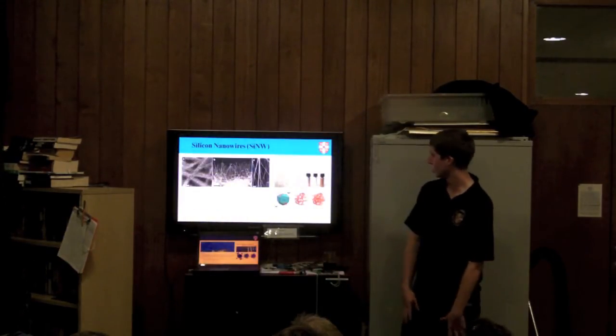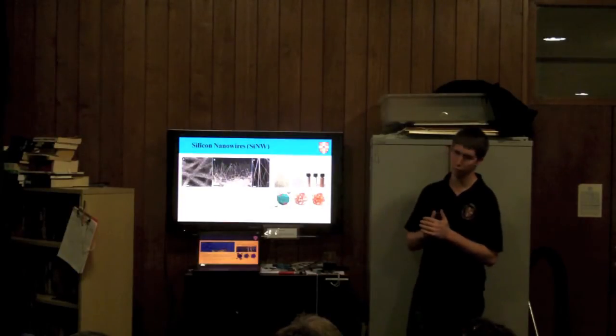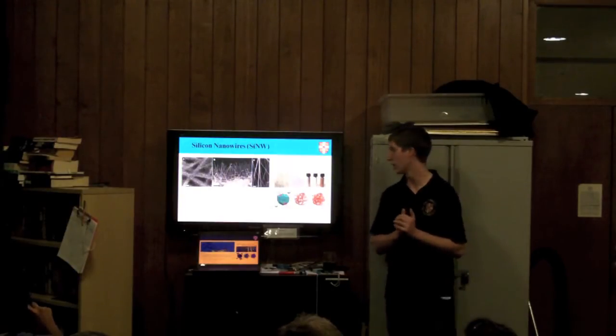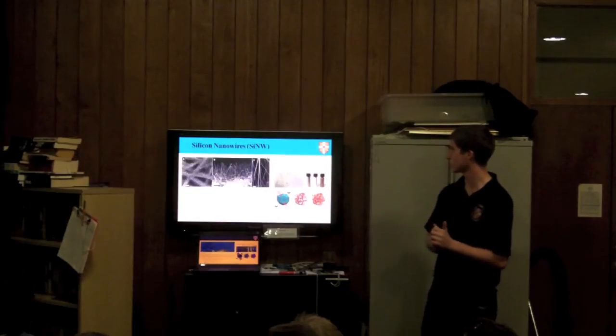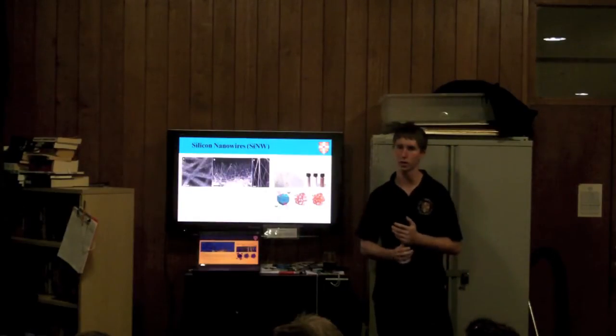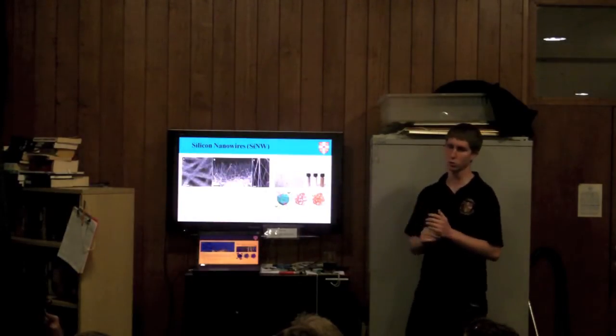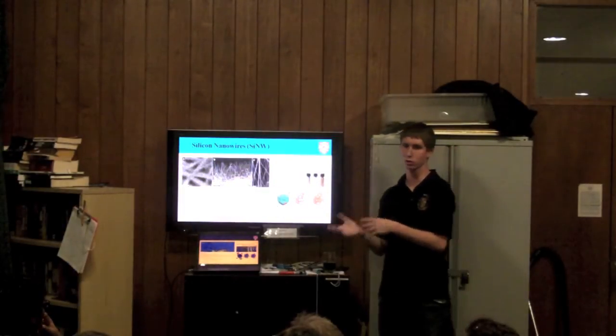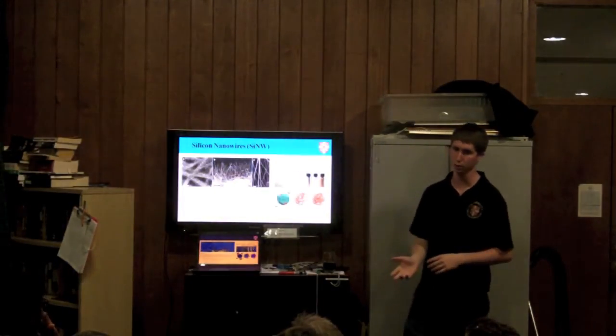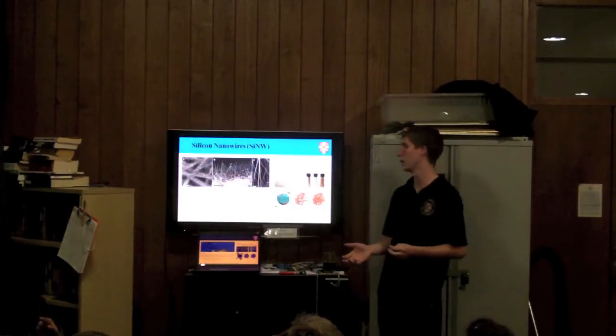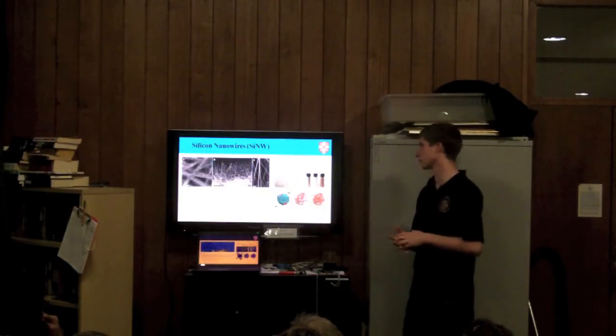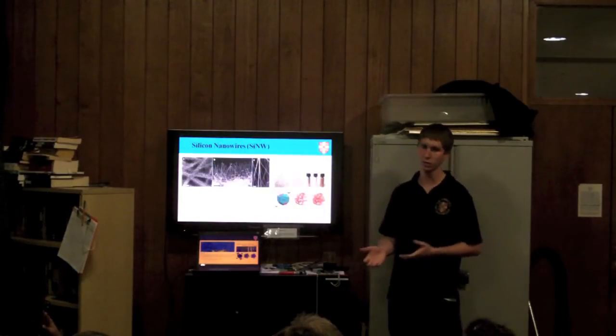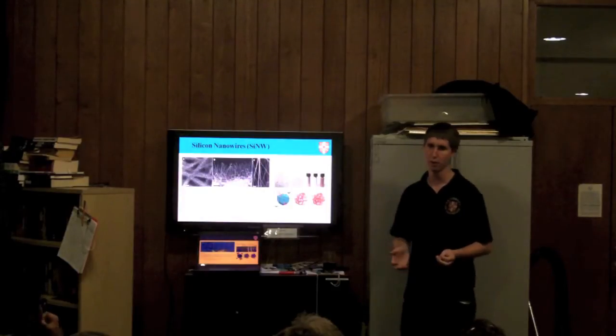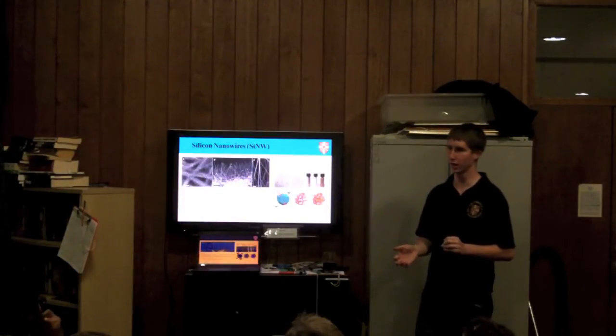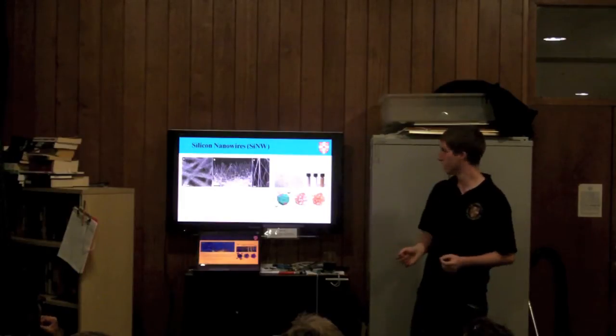And then we'll get into a couple more futuristic things here, but they're really interesting. So this is silicon, or silicon nanowires. Some things, like the lithium iron phosphate I showed you, are for the cathodes, but we do research on both the cathodes and the anodes because we want to make both better. So this is an anode, and this would be replacing the graphite. Graphite's obviously really cheap, but it's really crap. And so you want something that is equally as cheap, but works a lot better.